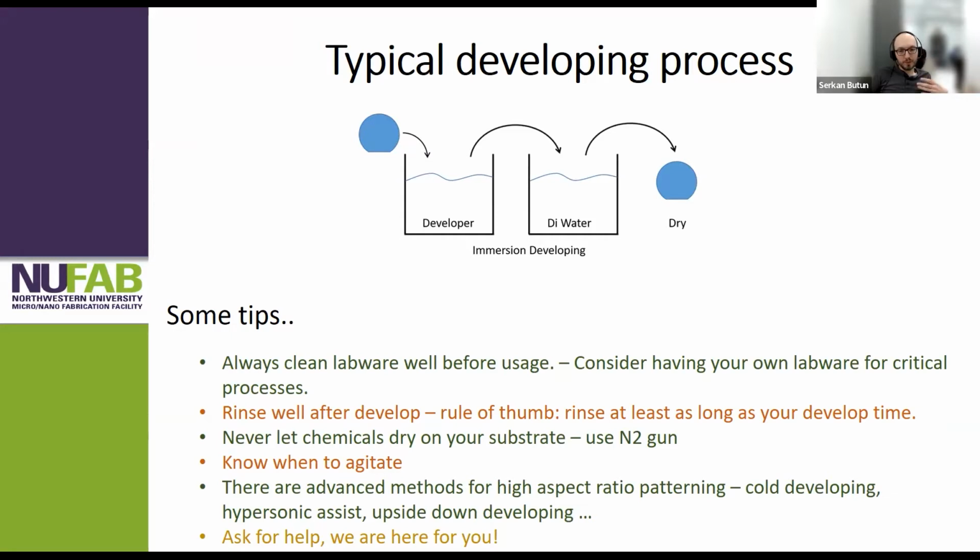And that's why we agitate it, to get fresh developer down deep in the grooves in the resist. However, this can be counterproductive if you are trying to make very fine, micron size features, because agitation is not going to be the same each time you do it, so you'll get inconsistent results from one sample to the other, right?